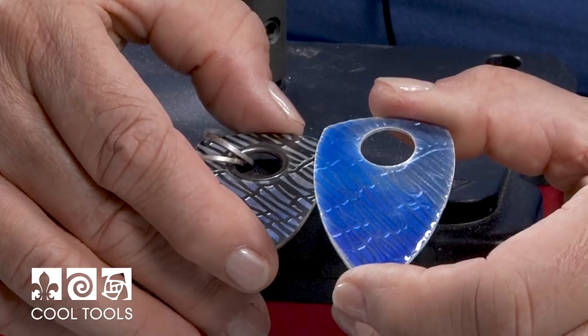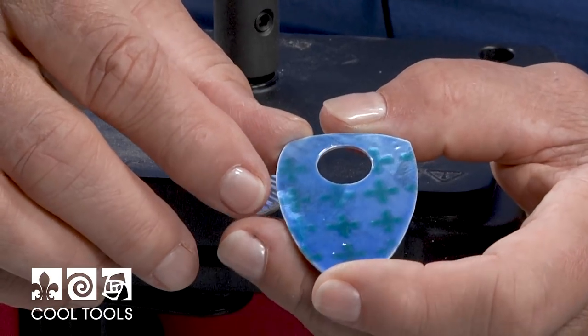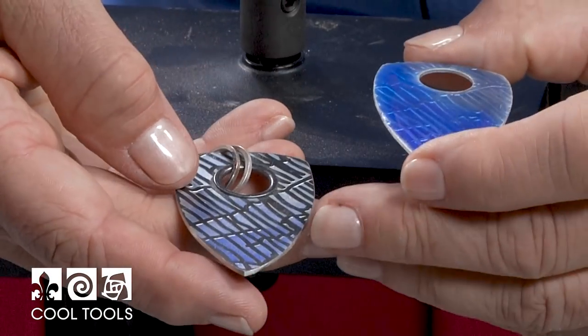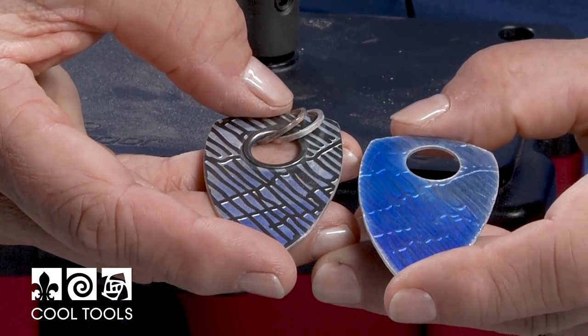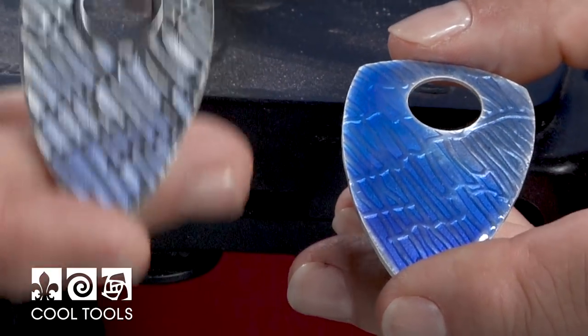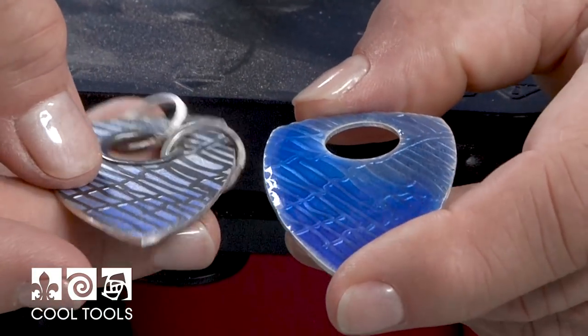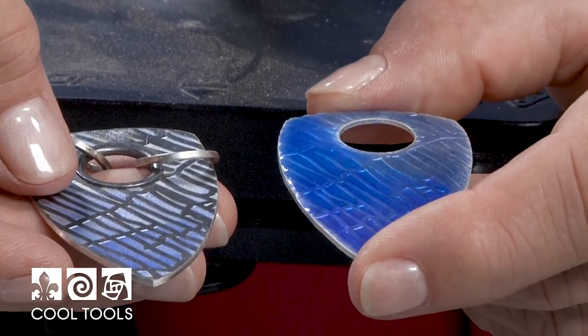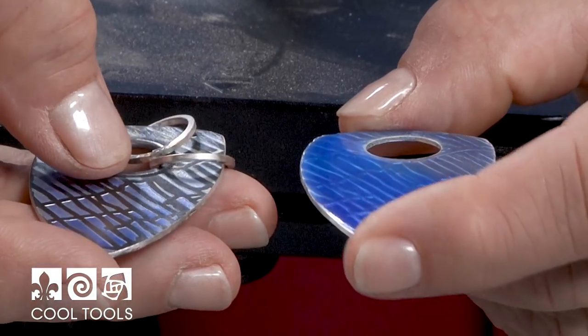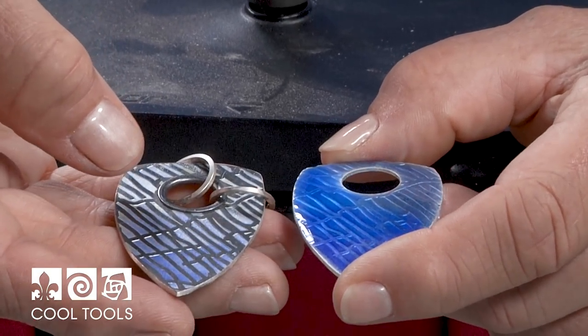I've put one additional coat of enamel on the front and I've also put my counter enamel on the back. I decided to put a little pattern that was different from the front so this could be a dual sided pendant. My next thing is to take this piece and make it into a Champleve. The difference between those two techniques: Champleve has exposed metal. So that black patina that you see on this side is a patina I'm going to put on — this is metal and this is all glass. When I do any grinding on glass, I want to be sure I have eye protection and a mask. This is silica. Some of it could be lead-bearing though the Thompson line we're working with today is lead free. But it's always good to take care of those body parts you don't get a replacement for.